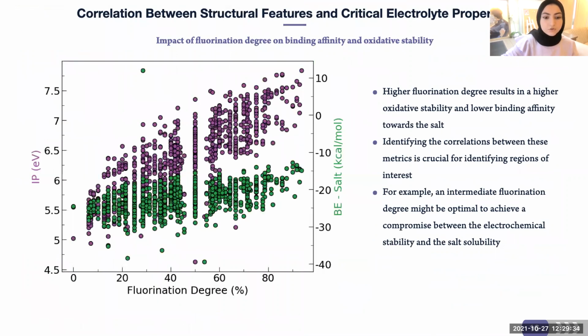And with this approach, we were able to identify correlations between the predicted properties. For example, we found here that a higher degree of fluorination on the x-axis can result in higher ionization potential on the y-axis, or oxidative stability of the solvent, but a lower binding affinity towards the salt. So establishing these kinds of correlations is critical in order to identify regions of interest in space. Here, an intermediate fluorination degree might be optimal to achieve a compromise between the electrochemical stability and the salt solubility.